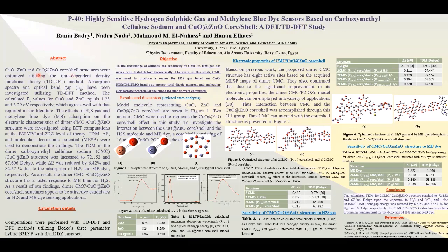Table 2 presents the total dipole moment values and the HOMO-LUMO energy for these two interaction mechanisms, and it confirms that the interaction proceeding through the oxygen atom of the shell is the most prominent one, as it has the lowest HOMO-LUMO band gap energy.